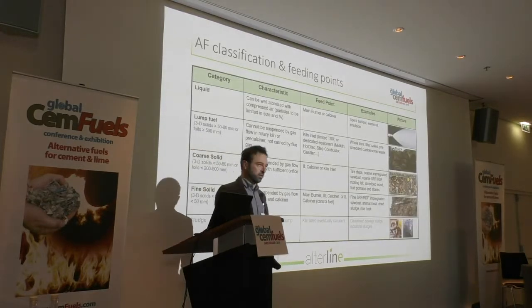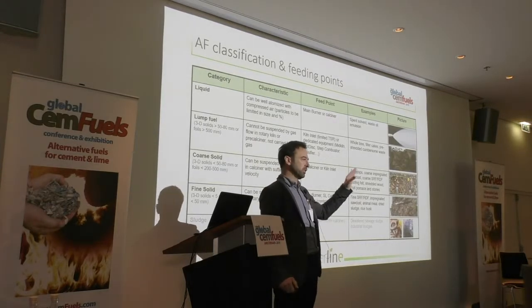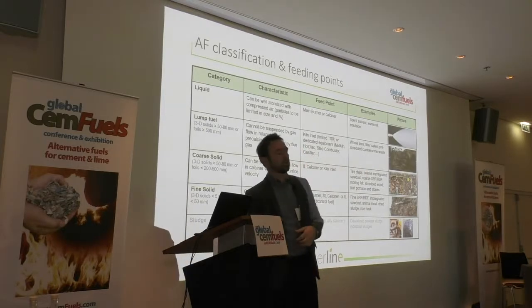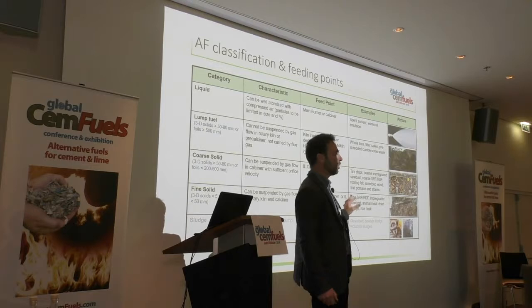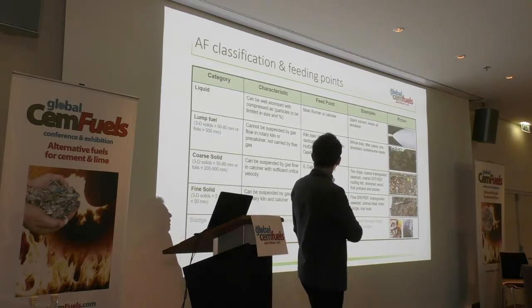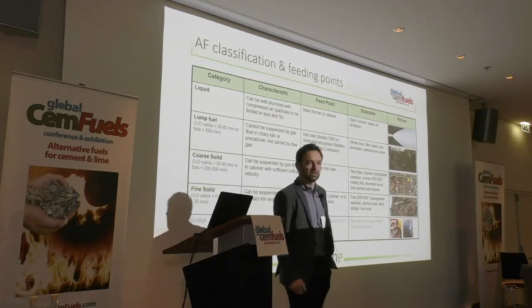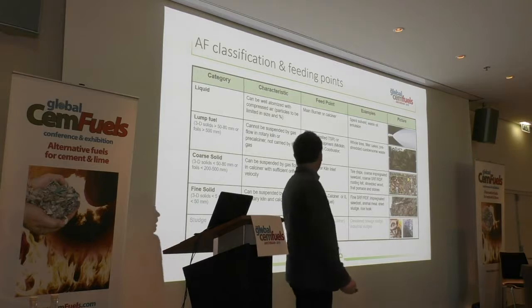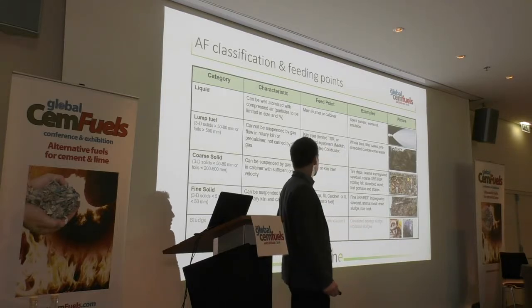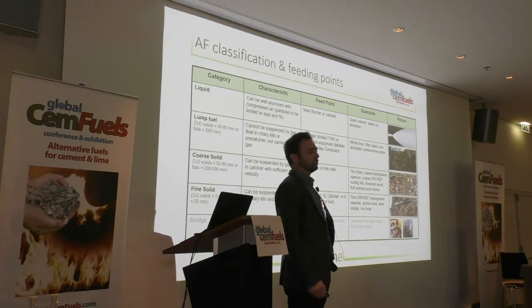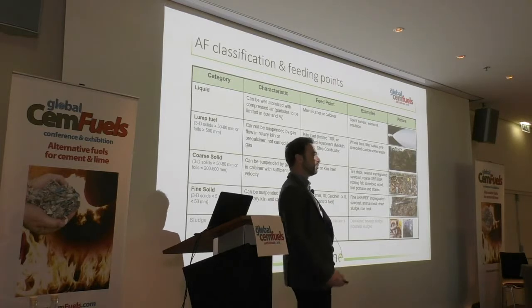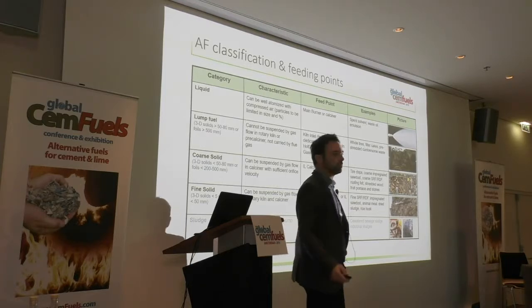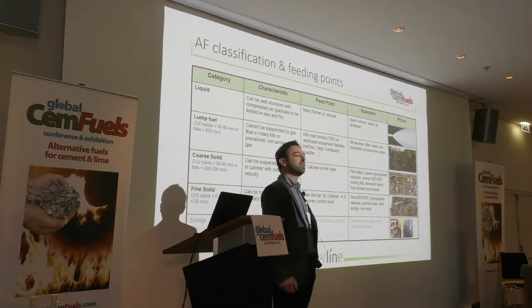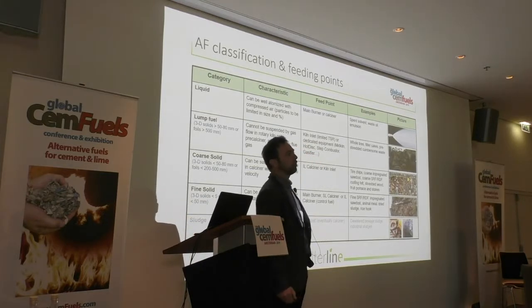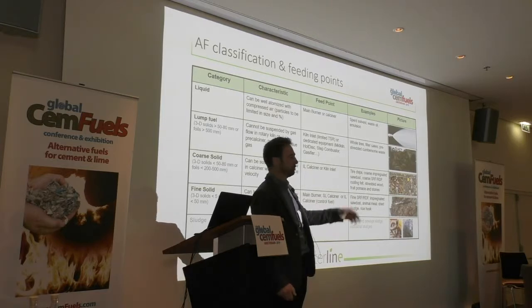The classification quickly of the alternative fuel: you can classify it by physical properties, let's say liquid, sludge, solid, or you can classify it by feeding points. Liquids, let's say, if there are no particles in the liquid, it's not a big deal to inject it. It can be done at the main burner or at the calciner, depending on the liquid. Lump fuel is fuel which is too big, too heavy to be suspended in the calciner. Of course, you cannot move it pneumatically, so it will be put at the kiln inlet in a limited way, let's say, limited substitution to avoid reducing conditions.